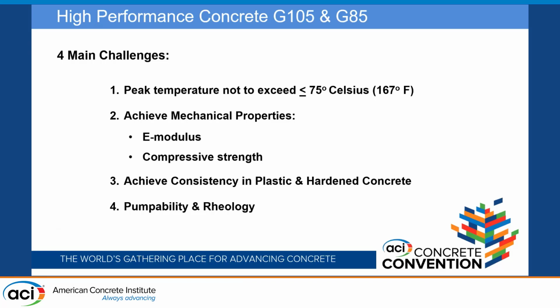The concrete batching, as you can imagine, with some mass placement such as this, was critical. There were obviously the temperature requirements. To achieve the max temperature of 167 with these high strength mixes, the concrete batch plant itself used ice feeding the plant. And in some instances on the very critical placements, 100% ice was used for batching, no batch water, just all ice. And to feed that, they had an ice plant basically built and set up right next to the ready mix plant on site.